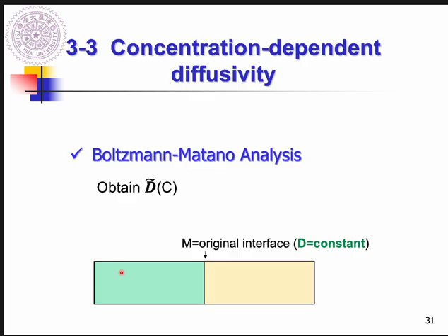In the beginning, you heat these materials up and allow interdiffusion to happen. At your time point of interest, you stop the diffusion process. Then you section the sample to get the concentration profile for A, and plot how the concentration of A atoms changes with location.